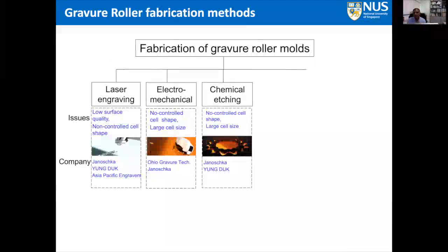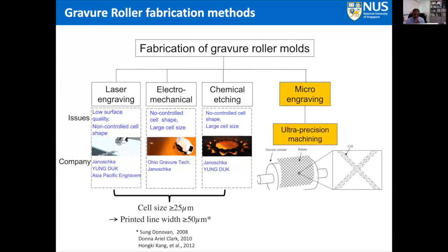Okay, so we went on to fabricate the Gravure roller mold. Primarily in the industry, people use laser engraving. People also use electrochemical and electromechanical systems. Also, people use chemical etching. These are some of the companies that are very specialized in this. People make very fine, very intricate features. But the only thing is that they are able to machine a cell size, that means an individual pixel, of about 25 micron. And when you make these cells, which are about 25 micron, the printed line width after you pass through the ink will be about 50 microns, which is relatively thick.